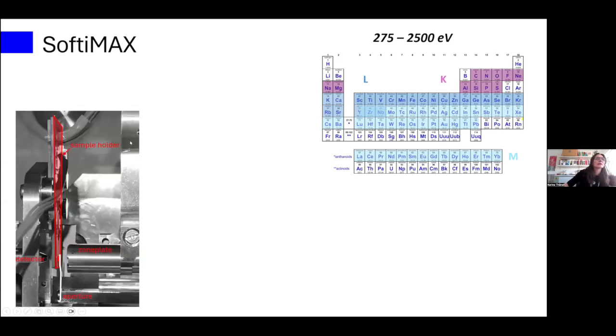How does it then look inside our end station? Well, typically, this is what we have when you look in from the side. By now, maybe the beam is coming from the other side. So the zone plate is mounted on the very end here. Here is the order sorting aperture sticking nicely in between the two. And then the sample plate, this massive thing with the sample. And then the detector, you can just see the tip of it, is behind here. Now, this distance from the sample to the zone plate is a couple of millimeters, right?